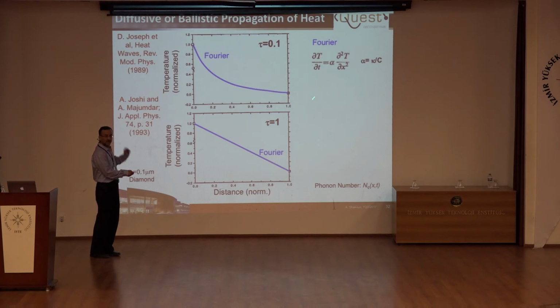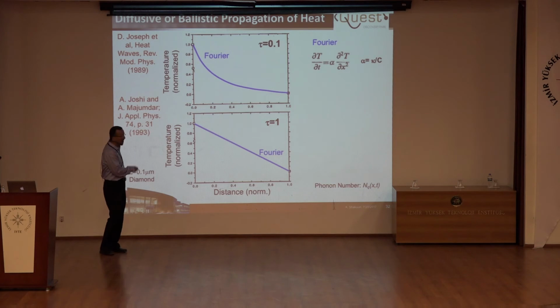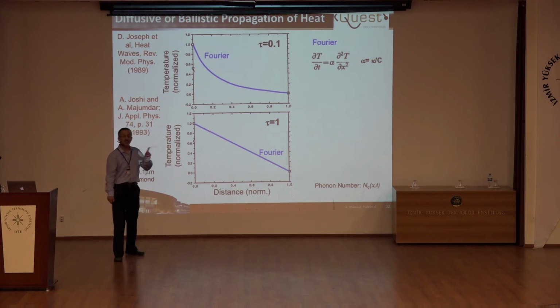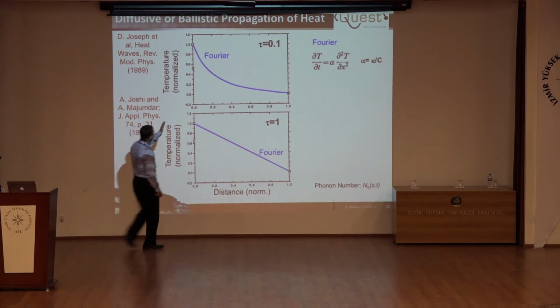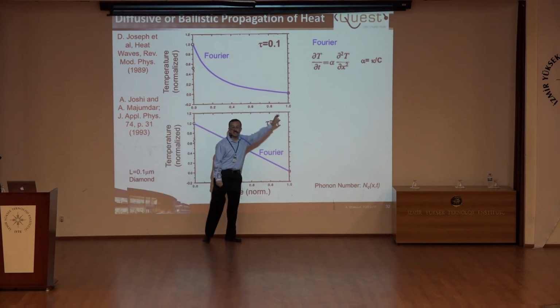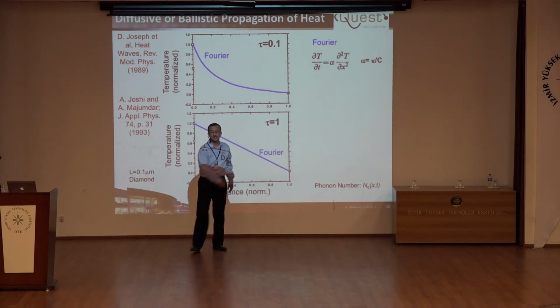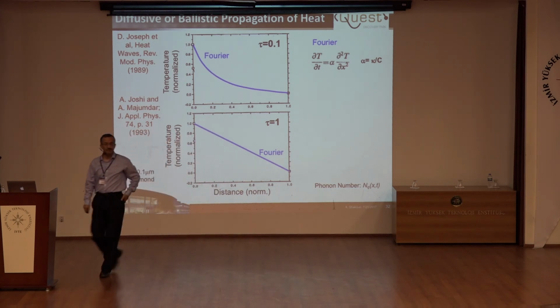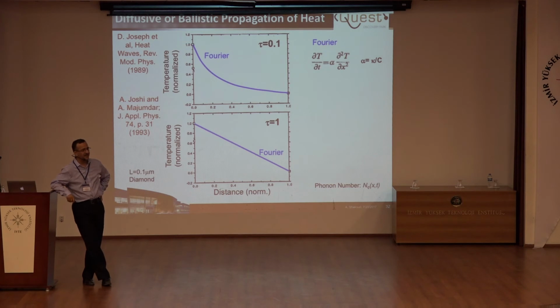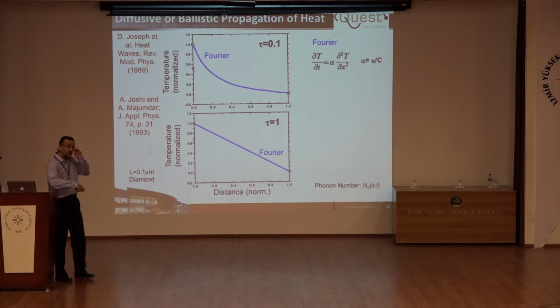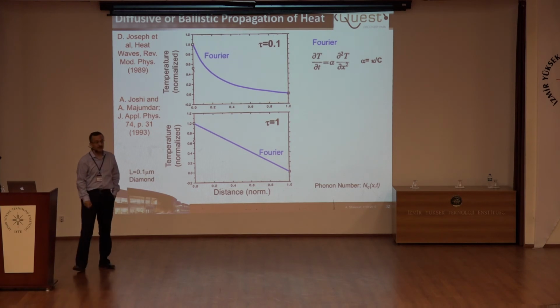everywhere is the same temperature. I apply a pulse of heat here. Temperature increases and you get this profile at early times, this is normalized time. At later times, you get the steady state and you can define thermal conductivity. But at time 1 femtosecond after the heat pulse, temperature everywhere in the field is non-zero. The information at this boundary has propagated everywhere in the sample instantaneously, and that's the characteristic of this differential equation. There's nothing else you could do. And you know Einstein would not have liked it, correct? There's something called causality. How do you introduce causality? This equation is not causal.